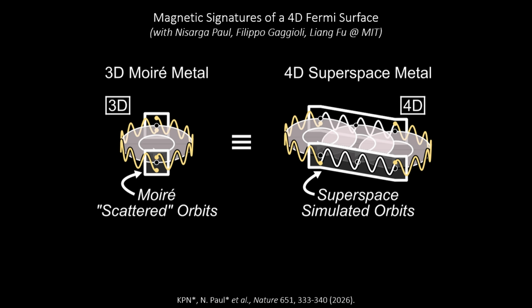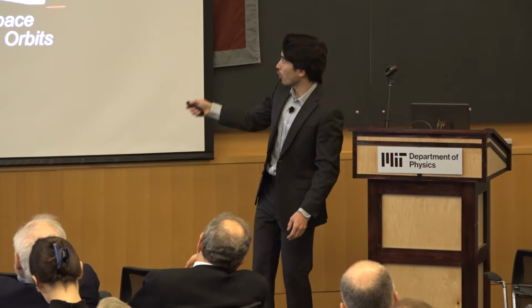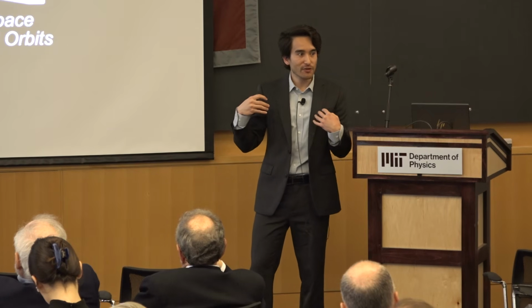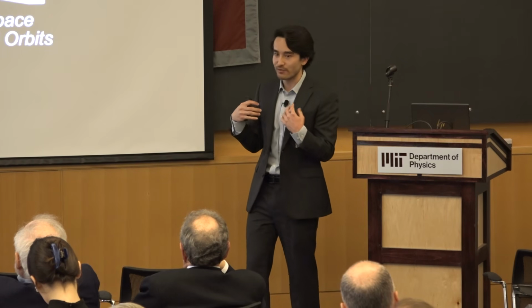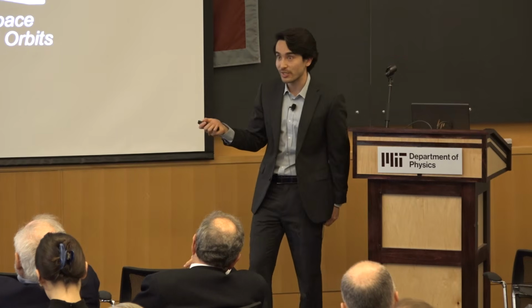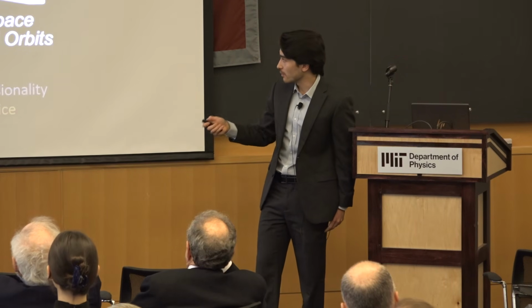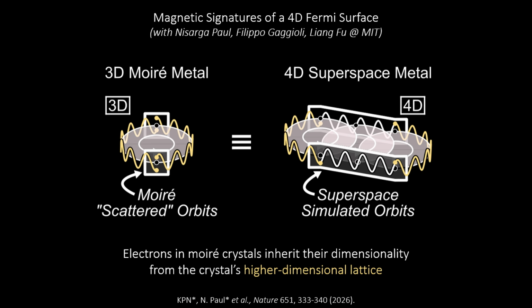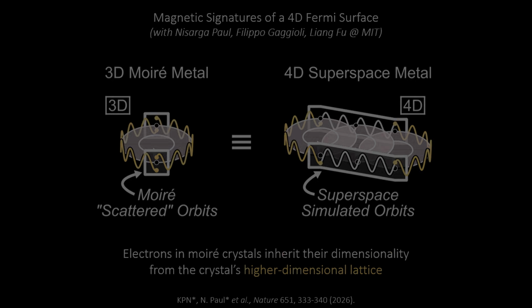But an alternate approach was to recognize that hidden in the mathematics of that calculation was the material's four-dimensional lattice. We found that what looked like, in this rigorous calculation, simulated orbits of a four-dimensional superspace metal, as if I had done four-dimensional measurements in a 4D metal. And what we're looking at are effectively projections of the physical observables from 4D orbits down into 3 dimensions. And so this offers us a perspective that perhaps Moiré crystals can be thought of as perfect simulators of some of the properties of higher dimensional quantum materials, because the electrons in these crystals appear to inherit their dimensionality from this higher dimensional lattice.